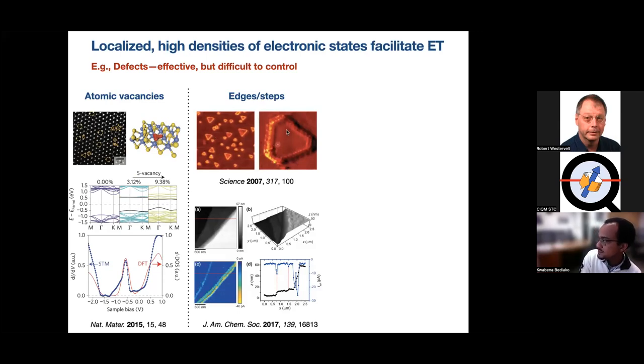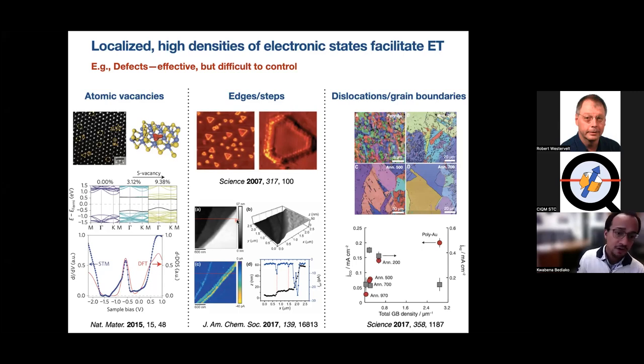Not just atomic vacancies, but steps and edges of materials have been shown to be effective at mediating interfacial charge transfer and catalysis. And then there are also examples of other types of defects, dislocations, grain boundaries, that you can imagine would have distinctive electronic properties that would then lead to interesting chemistry. And that is indeed what you see.